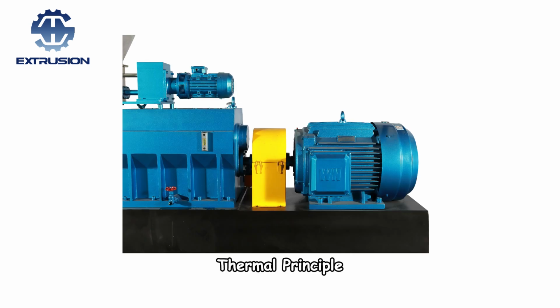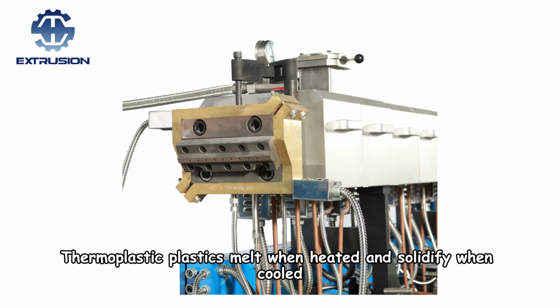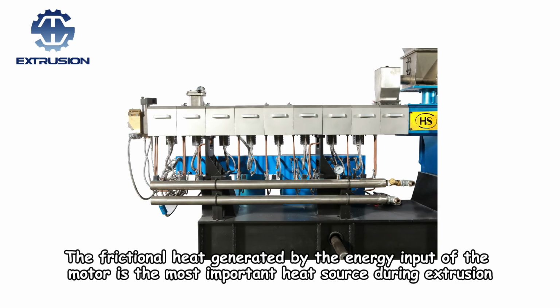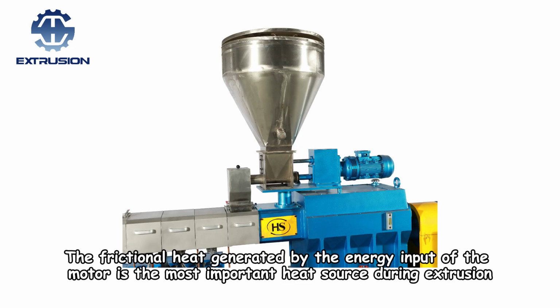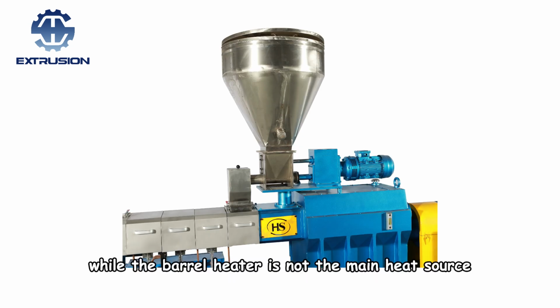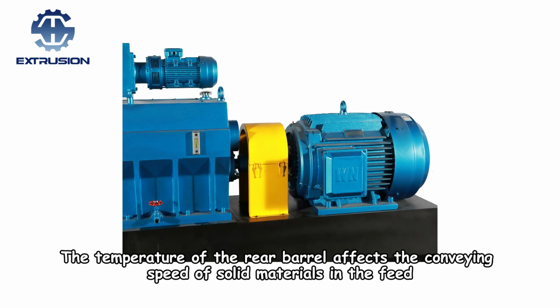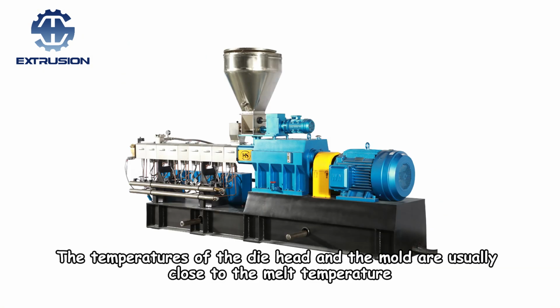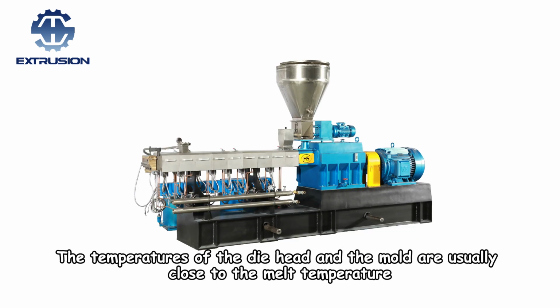2. Thermal principle. Thermoplastic plastics melt when heated and solidify when cooled. The frictional heat generated by the energy input of the motor is the most important heat source during extrusion, while the barrel heater is not the main heat source. The temperature of the rear barrel affects the conveying speed of solid materials in the feed. The temperatures of the die head and the mold are usually close to the melt temperature.